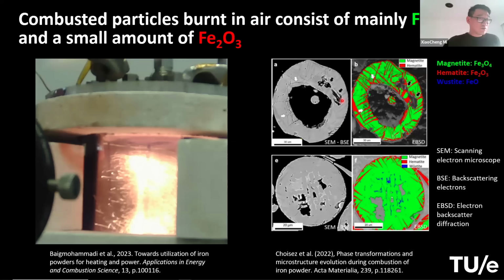Actually, it doesn't go, yes or no. Actually, it does go away every time you combust it. Because once you ignite it, when it goes into liquid phase, the surface tension will make it spherical, as a compact sphere anyway. But this is not true for most of the particles. Some of the particles go spherical, but when you do the cross section, you're going to find some of these inside. They may not appear at the surface.